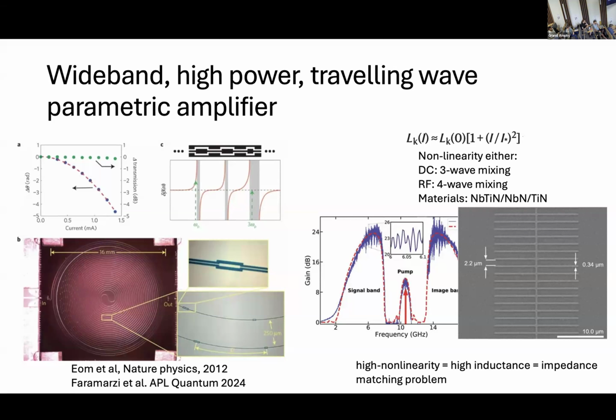The first paper here is by Peter Day et al. You see that this is a device that is, I think, centimeters long in total, with a niobium titanium nitride wire that is completely rolled up to fit on a chip. Here they explore with a DC current how much nonlinearity, or how much phase shift, they get as a function of current, which relies mostly on the I-squared nonlinearity that you will have in any system at some point. And there are two versions that you can make there.